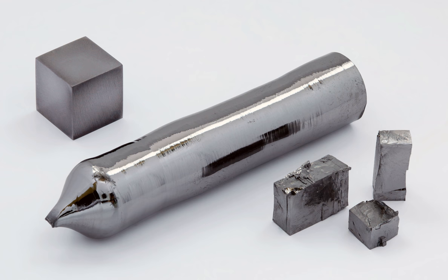In modern times, the separation is achieved by hydrometallurgy. Extraction begins with leaching the ore with hydrofluoric acid together with sulfuric acid or hydrochloric acid. This step allows the tantalum and niobium to be separated from the various non-metallic impurities in the rock. Although Ta occurs as various minerals, it is conveniently represented as the pentoxide, since most oxides of tantalum(V) behave similarly under these conditions. A simplified equation for its extraction is thus: